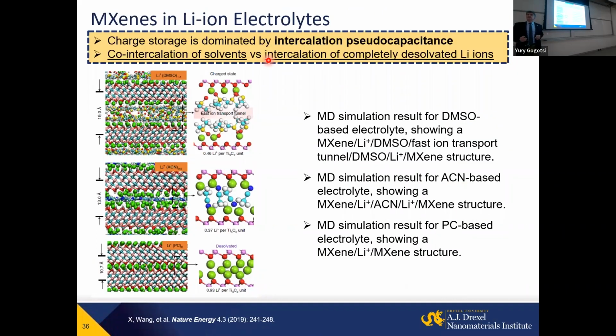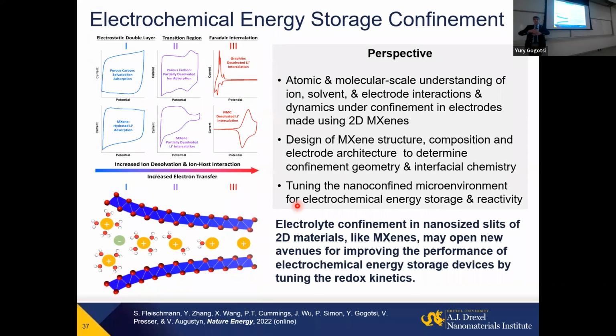Moreover, there are of course a lot of challenges. For example, depending on the type of solvent we use with ions, we can get situations where ions co-intercalate with the solvent, or we can get complete desolvation and go just pure lithium ions into the layers. So again, with 2D materials, we can go all the way from double layer capacitors to batteries simply by controlling desolvation of ions that intercalate between the layers. We just published very recently this perspective article in Nature Energy describing it. So again, you can do engineering not just by taking discrete materials, but by controlling the nanoscale materials and electrolyte use.